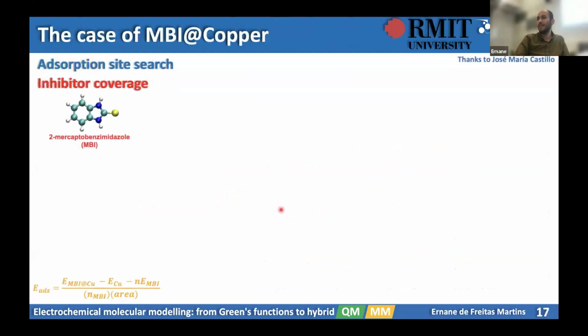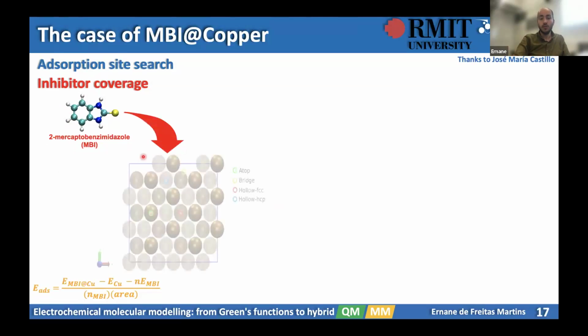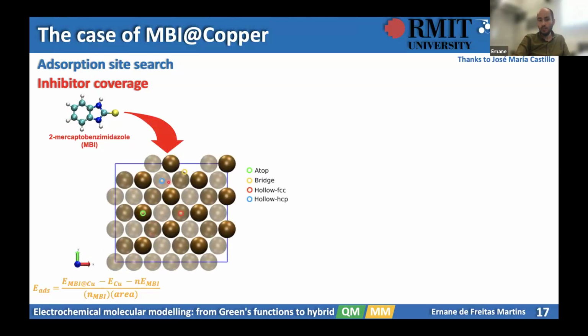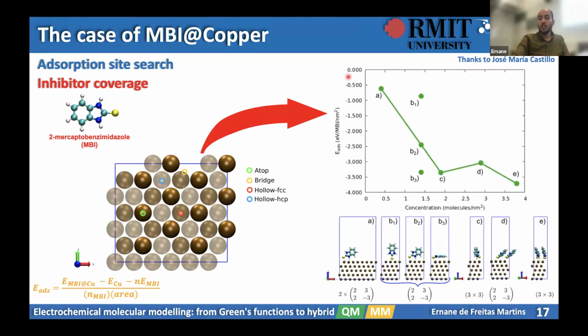Now, this is what Jose Maria did in the beginning of his PhD. The first thing he did was to evaluate the interaction between this molecule, which is a corrosion inhibitor for copper, and a copper surface. He made an adsorption site search. He tested several different positions of this molecule above copper, and also changed the coverage, so the amount of molecules and the shape of the box, to end up with an adsorption energy as a function of the coverage, like in this plot. As we increase the coverage, we can clearly see that the adsorption energy decreases, so the system gets more stable. The formation of a self-assembled monolayer is stabilizing the system here.